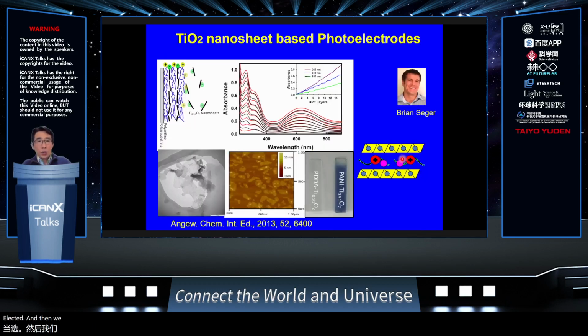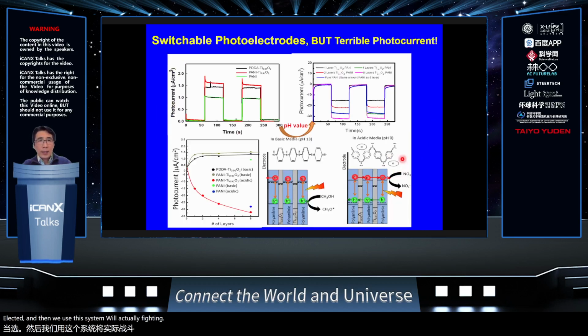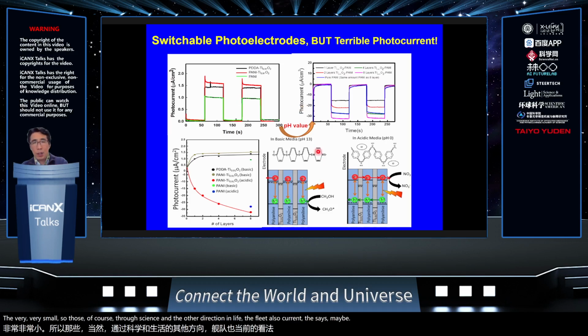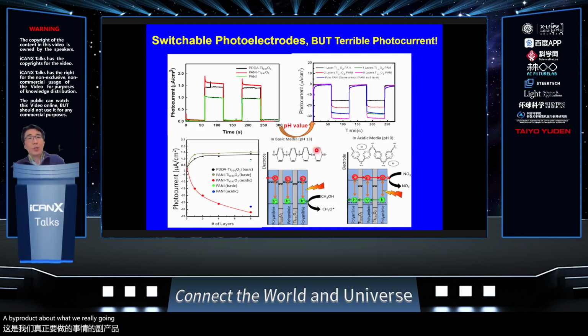Then we used this photoelectrode to check the photocurrent. Unfortunately, the photocurrent generated on this photoelectrode was very, very poor. Of course, we found some other side reactions, like a switch of current, that's maybe just a byproduct. But what we really wanted was to see how we can improve the photocurrent of this system. It was in the microampere per square centimeter range. The theoretical photocurrent of TiO2 is in the milliampere range, so we were about 1000 times smaller.